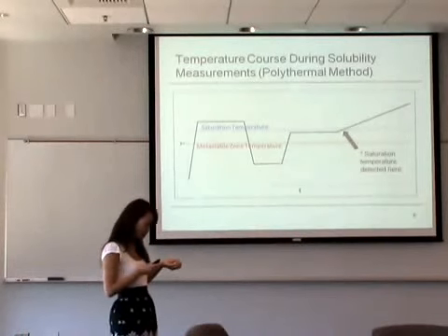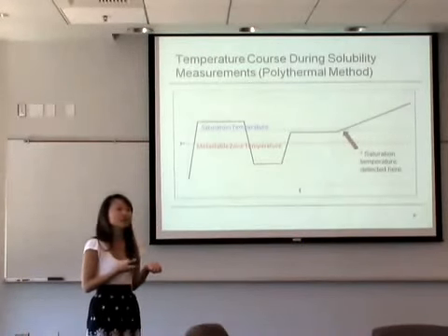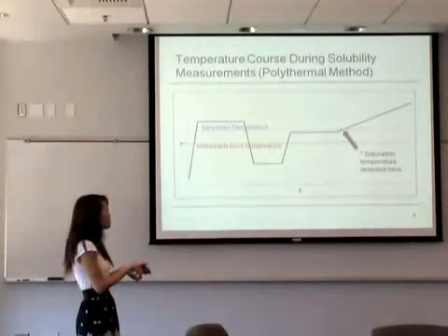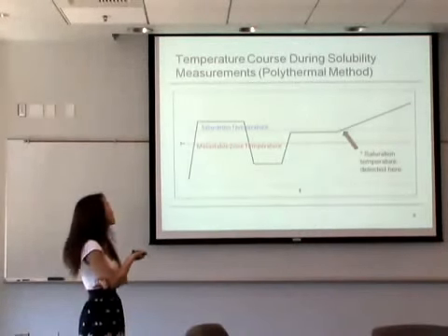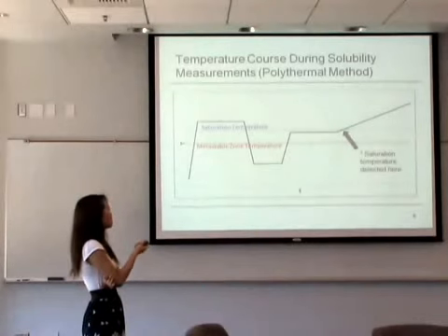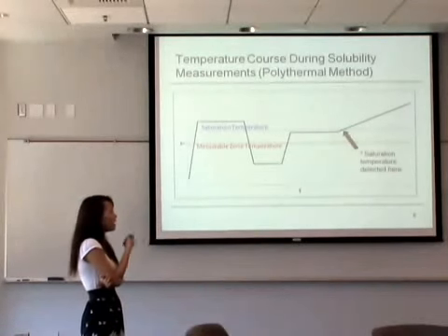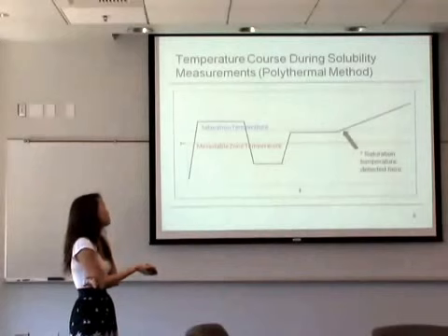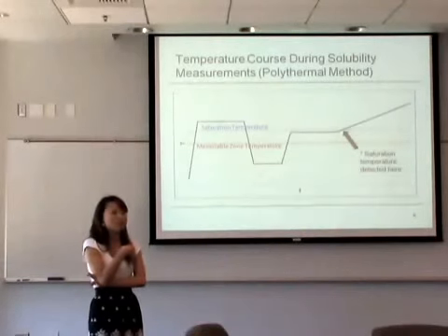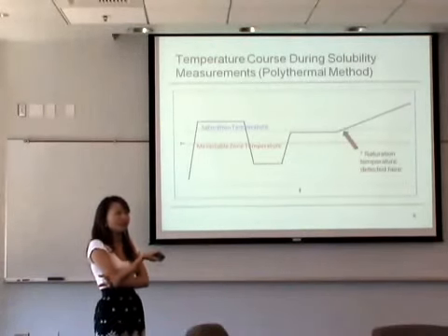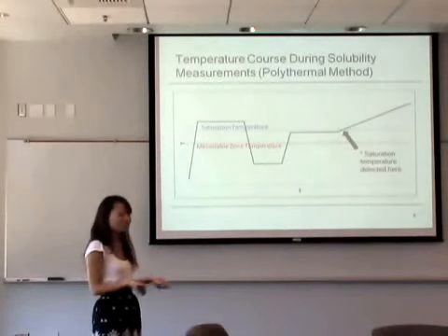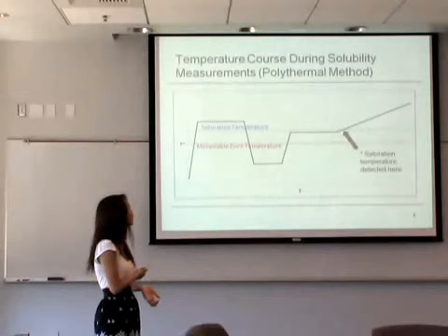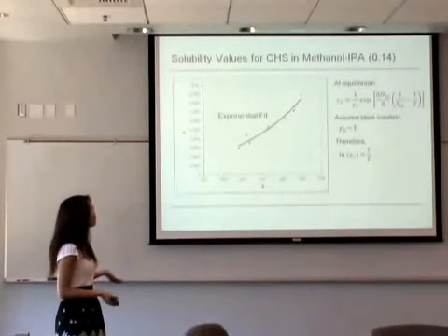These crystals are really tiny, so I can just dissolve them. I hold that until it reaches equilibrium, and then I raise it back up to right underneath the saturation temperature, and wait for it to reach equilibrium again. Then I increase the temperature by approximately 1 Kelvin per hour until all of the crystals have dissolved, and I can therefore say that this is my saturation temperature.